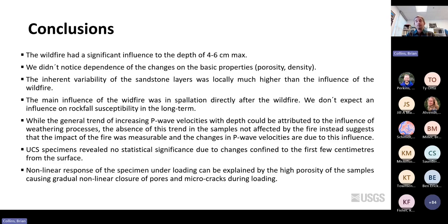We also have seen that using ultrasound measurements of P and S waves can give us better results than the mechanical testing, especially with highly porous samples that were already disturbed by the wildfire, we weren't able to extract nice results from that. So that is basically what we have found, the effect of the wildfire on the rock.